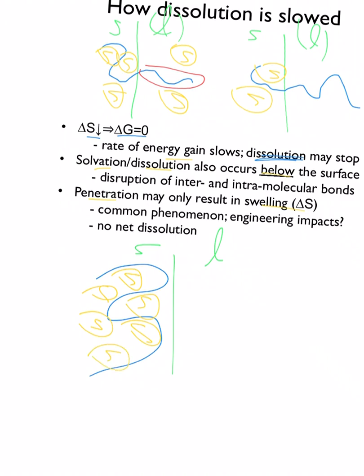Cross-linked plastics will do this too. Because they're cross-linked doesn't mean they don't like that solvent. Solvent can go into its structure. They can't come out because they're three-dimensionally cross-linked, but you can get this issue of swelling, which usually means the plastic is not going to work anymore because now it's got this layer of jelly that consists of both polymer and solvent on that surface. So that's kind of the end of that plastic in terms of any type of load-bearing application. But this does happen quite a bit.